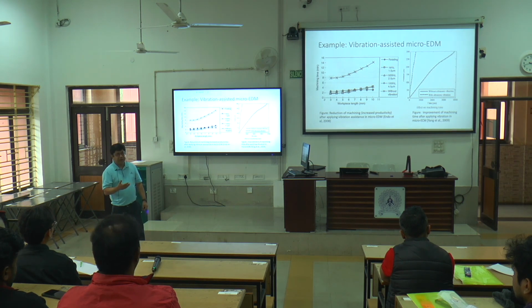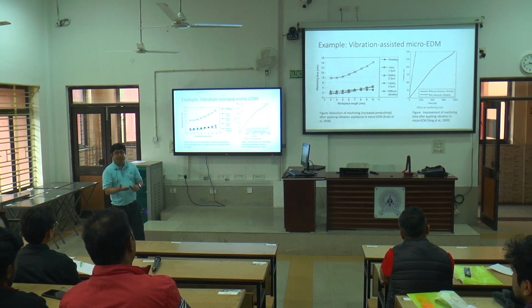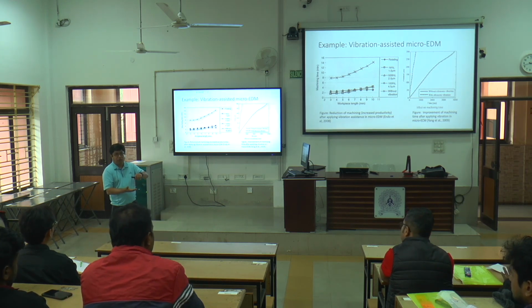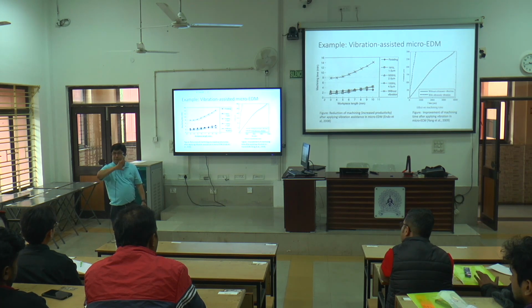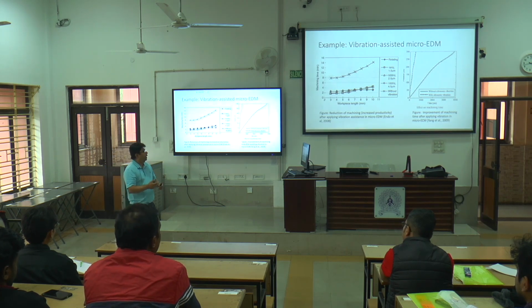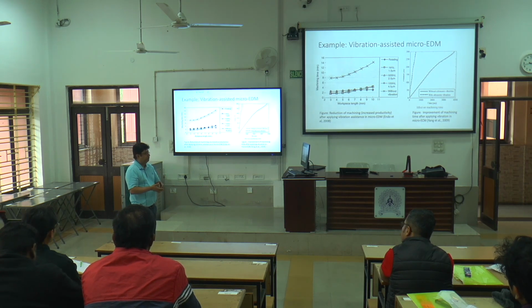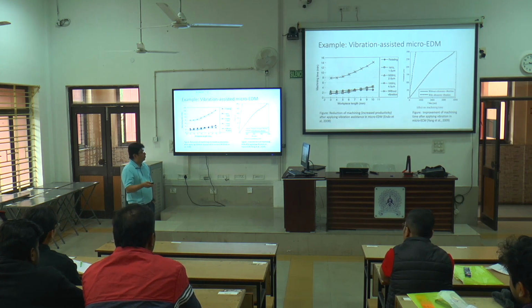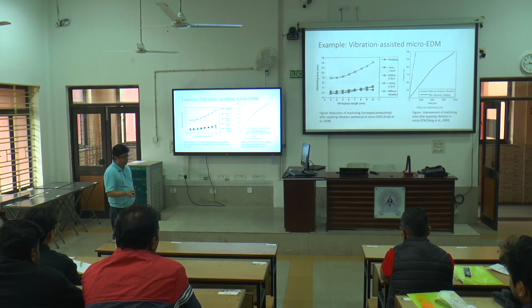So if you are using vibration assistance, definitely it creates some pressure. I think if you search vibration assistance, I have several papers, and one of them is a modeling paper. So it creates some sinusoidal variation of the pressure. When the gap is closing, you have an increase in pressure, then you have a decrease in pressure, right? That also helps to get the debris out, and it improves the spark efficiency. So there are several phenomena happening, and definitely machining time reduces, the material removal rate increases, the surface finish improves, and I think we found that the accuracy is a little bit off form, but the edges or surface finish is very good.